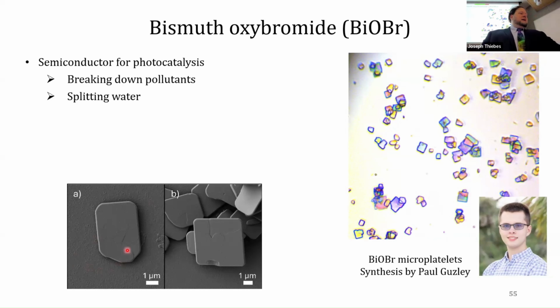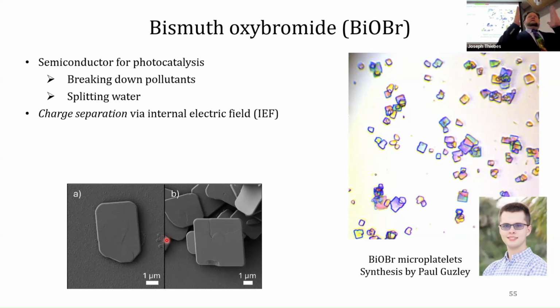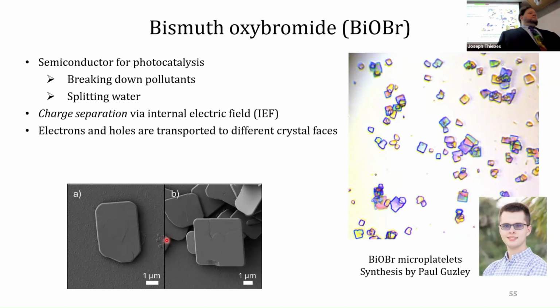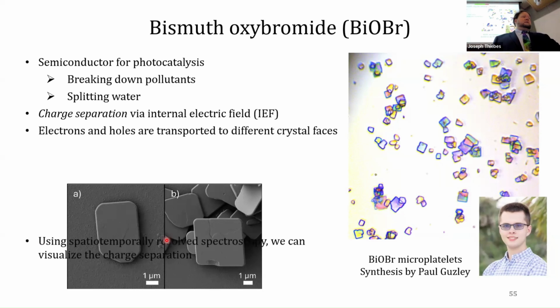And so this is the SEM. You can see the characteristic rectilinear shape of these. This one on the right, these oblique angles are because they're sitting at angles. You're seeing some perspective there. These are actually right angles. And you can see they have this flat, thin appearance, and that is due to the crystal structure. These have been found to have charge separation through the internal electric field of the material. Within the material, it all cancels out, but at the surface, you get some band bending. At some surfaces, the bands bend up, other surfaces, they bend down, and because of that, you can get charge separation. The electrons and holes get transported to different crystal facets, and then you can do different kinds of chemistry in those different facets.